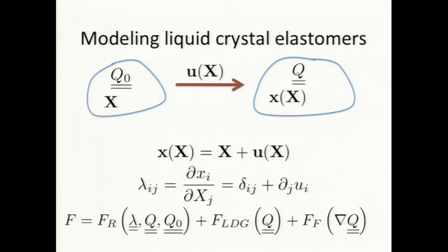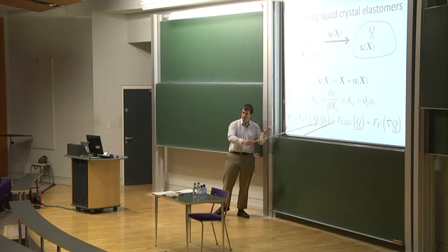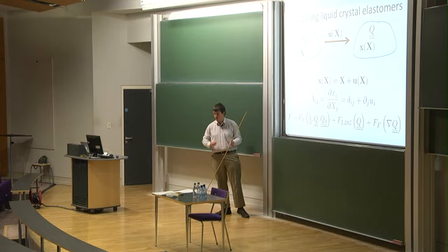And then we're going to think about the relative size of these two. So this one has order kBT per rod. This one has order kBT per chain. And there are many liquid crystalline rods for each chain. And so this is much bigger. So consequently, when I minimize this energy over magnitudes of Q, that's really a process dominated by this part of the energy. And therefore, going forwards, I'm going to forget also this part of the energy and rather replace this by a constraint which just says the magnitude of Q is fixed.